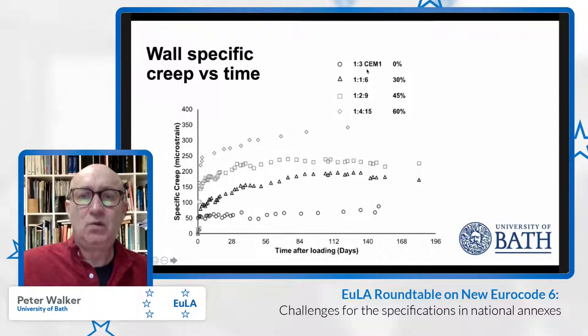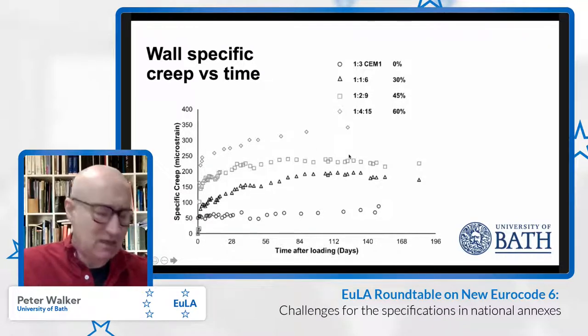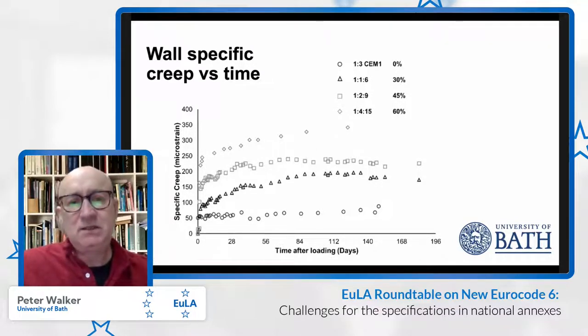for the four walls using the same medium water absorption clay brick in this case, and showing the relative specific creeps here for each of those four walls. And again, in keeping with the mortar tests, the creep was higher in the weaker mortars or those with higher lime contents. We can also see the creep rate also starts to level out relatively quickly in some